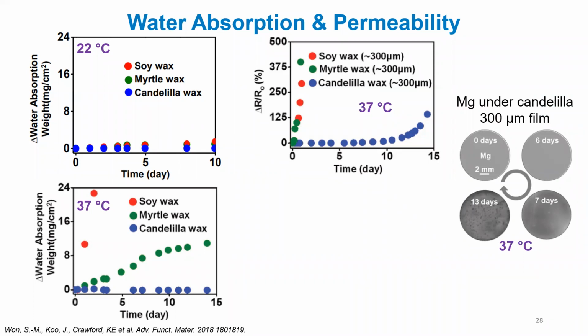We made these squares of magnesium film by a deposition method. And then we coated each of those with thin layers of the wax. And we waited to see how long it takes for the water to diffuse through and cause the resorption of the magnesium. So you can see the color starts to change around 7 days. And then we connected 2 wires to this so we could also measure the resistance, because as the magnesium is being resorbed, you have an increase in resistance, which you would expect to see.